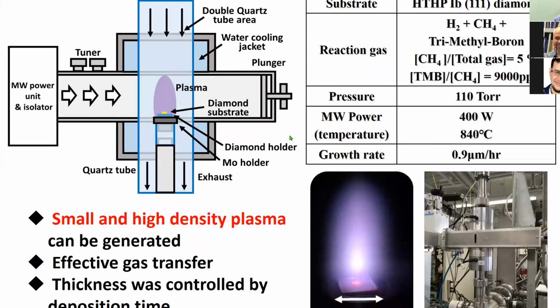The plasma we're making is very efficiently localized to certain regions, and this is one of the reasons why we get a little bit higher TC compared with other groups. The plasma is very focused on these regions - this is a microwave plasma.